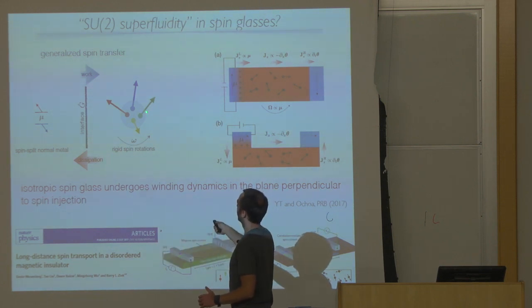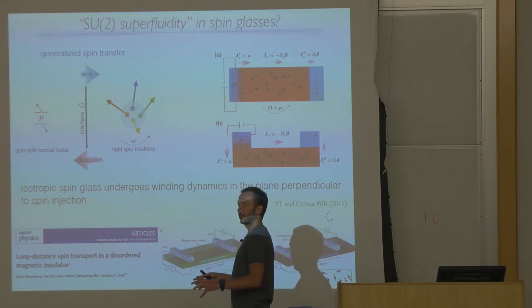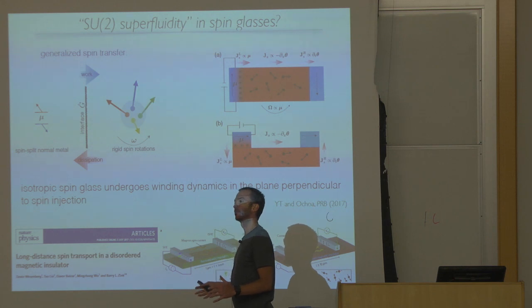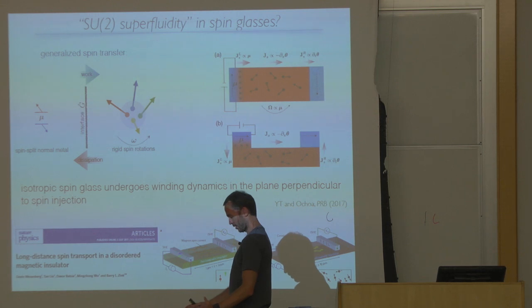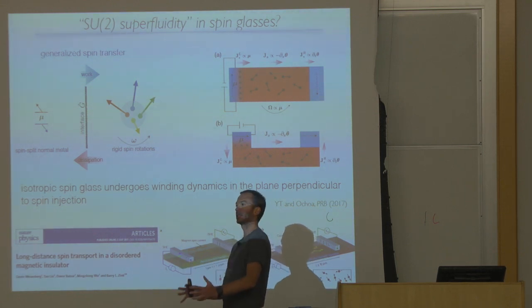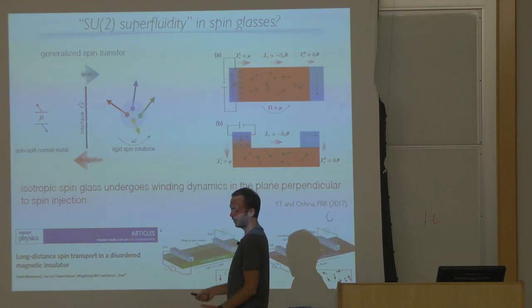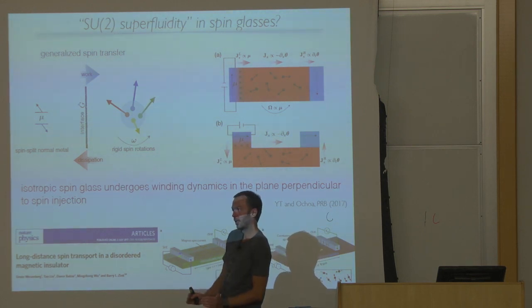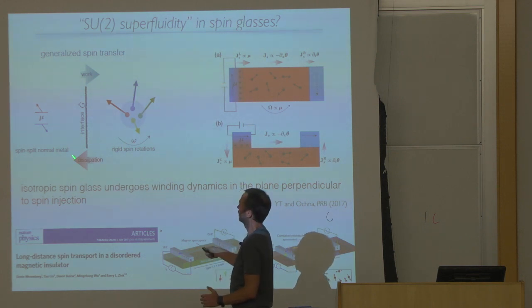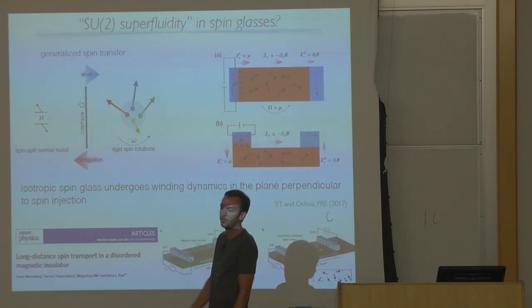Namely, locally you cannot move this spin, but so long as there's still global SU(2) symmetry, or approximately a global SU(2) symmetry, if you have a chunk of the material, globally you could move all the spins. Now if you apply some spin accumulation at the boundary of this material, all it does is it has this energetic tendency to twist your global arrangement around the direction of the spin accumulation. And that propagates basically as a superfluid, like before.